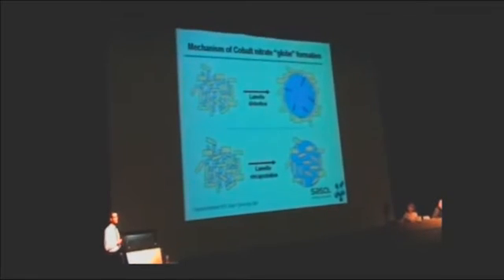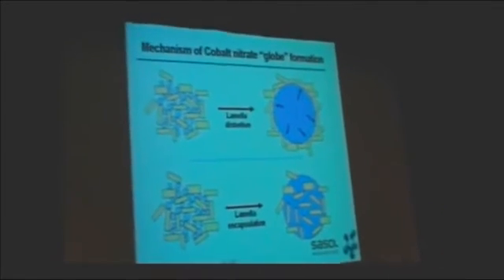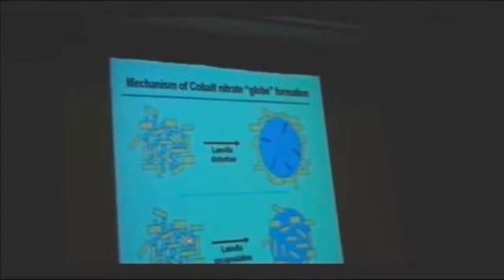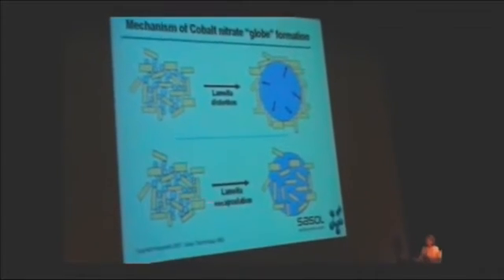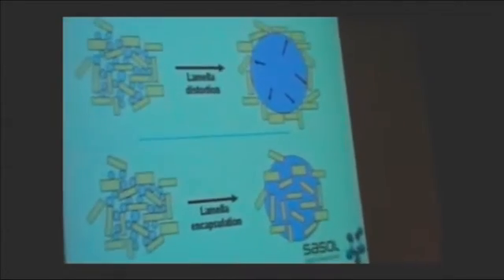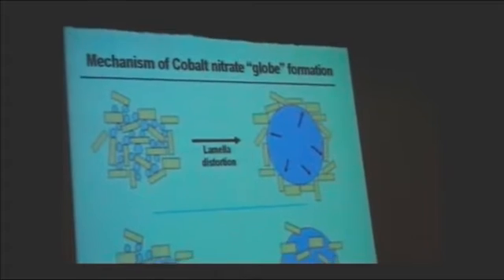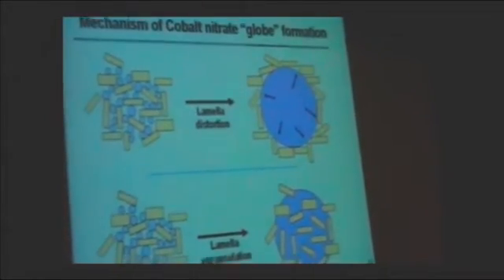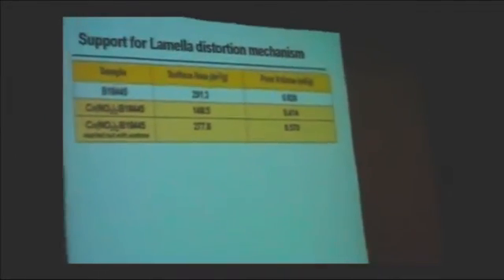So we can put forward two mechanisms. One where lamellar distortion is put forward as an acceptable mechanism, so the lamella is distorted outwards, you end up with this cavity in which cobalt nitrate is situated, and hence you can get droplets that are larger than the average pore diameter of your support, or a simple lamellar encapsulation mechanism where the droplets are just melting around this lamella. At this point in time, we support the first mechanism based on the following experimental evidence.